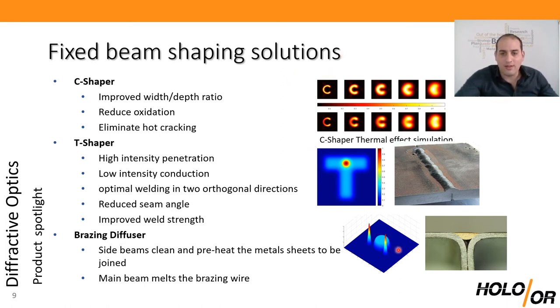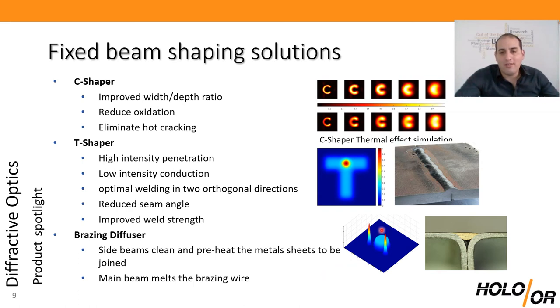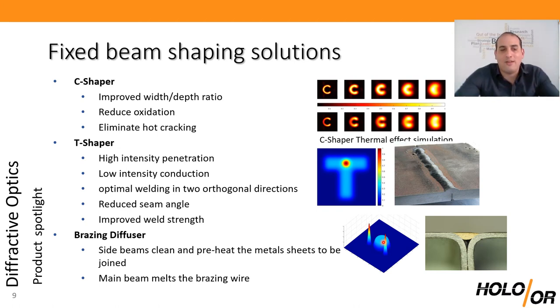Finally, the brazing diffuser. This intensity shape is used in the brazing of hot-dip galvanized aluminum or other metal sheets. The two outer spots clean and preheat the material while the central lobe melts the brazing wire, giving better braze quality. As anyone who has hand-brazed knows, if the surface is preheated the spread of the brazing material is much better.